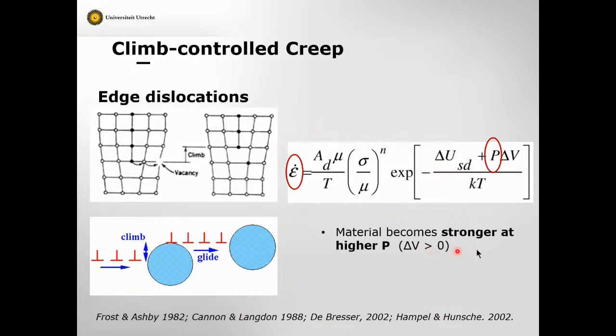And many people have done this. Here's one of these, interestingly, work done by Hans de Bresser and Nawaz Mohammed at our lab. In theory, these things should be dependent on the confining pressure, purely due to the effect of pressure on the structure of the dislocations. This gives a way to find out if this process is actually operating. But other mechanisms can control the rate. Climb can control it, that's this one. This flow law has strain rate with an exponential dependence on pressure. This is the stress raised to the power n, where n is typically 3, 4, or 5, and you see that in salt.